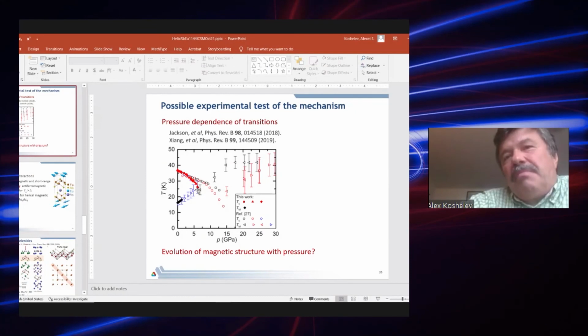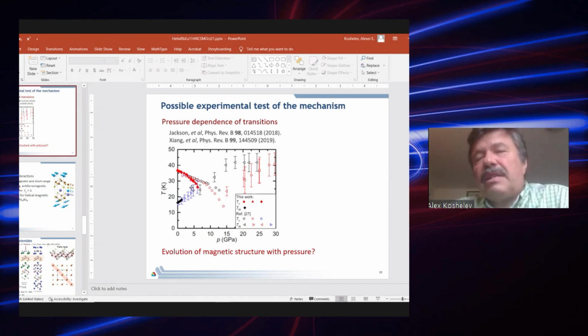Let me shortly interpret your last summary: the pi over 2 helix is a result of the compromise between the normal ferromagnetic type interaction, which tries to set the parallel orientation, and the antiferromagnetic pi orientation in the superconducting state. If this is correct, then in this inequality delta is a function of temperature. So would I expect that the helicity angle may change as a function of temperature as the superconducting transition temperature approaches the magnetic transition? This probably would be correct. I would think definitely in pressure, when the magnetic transition comes closer, you would expect that the Q vector would be bigger and bigger. This is the theoretical expectation.